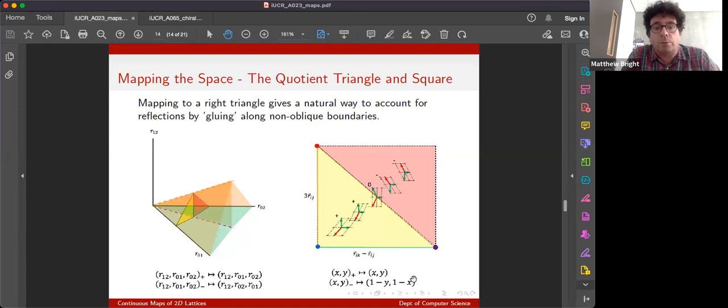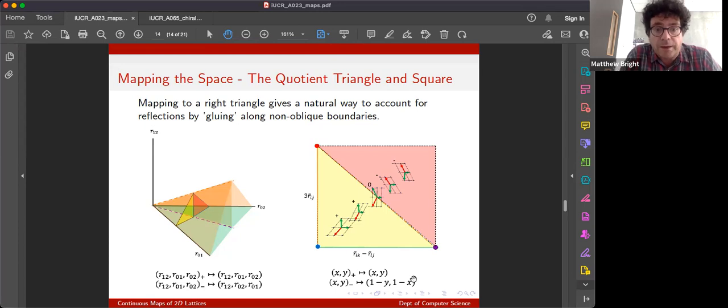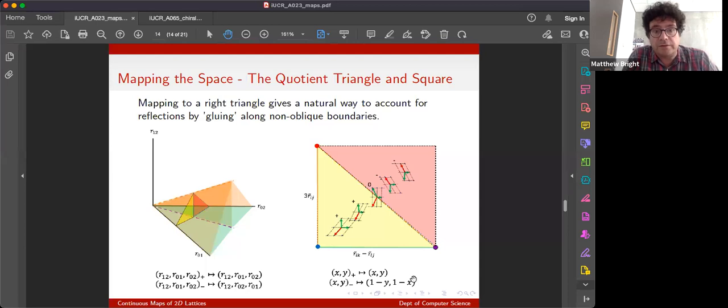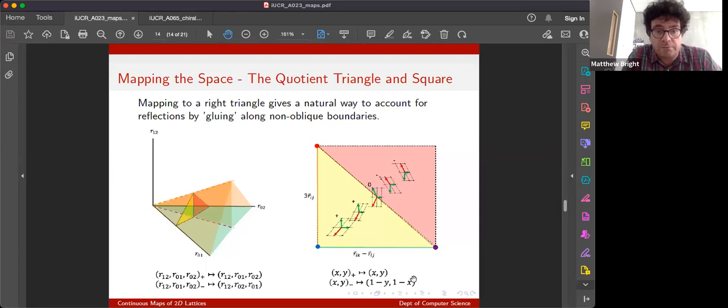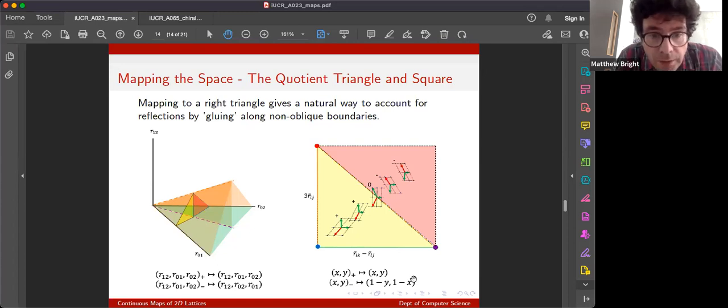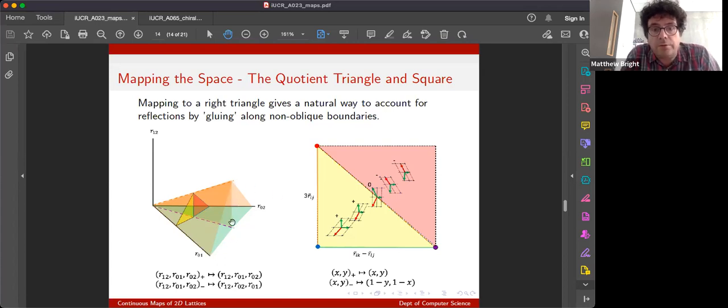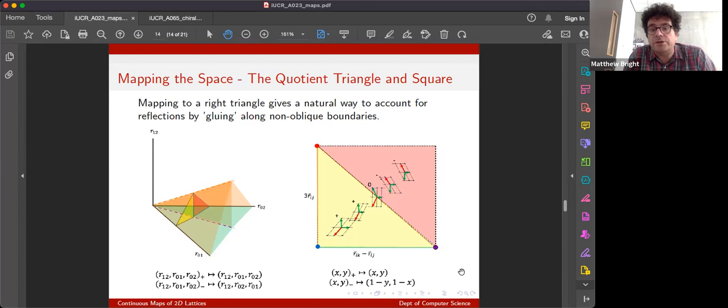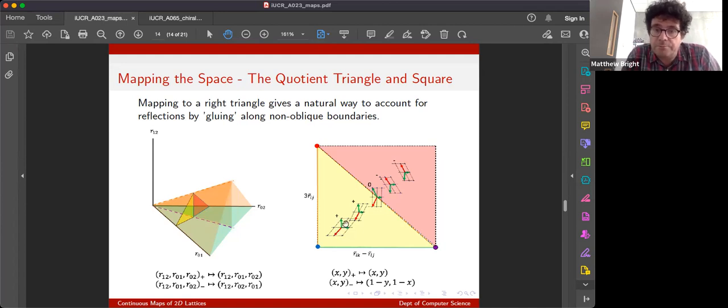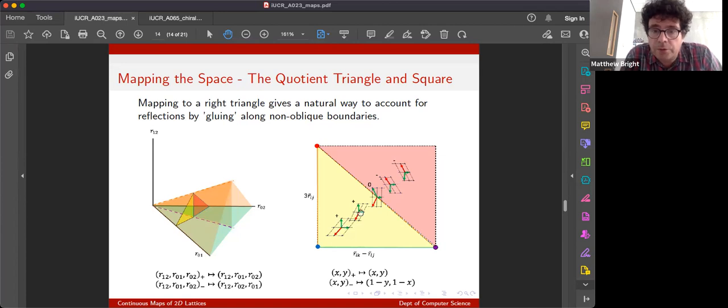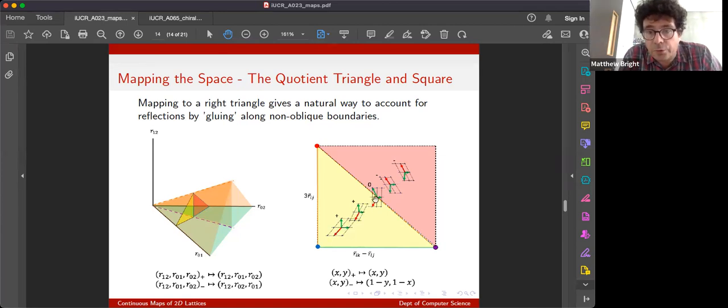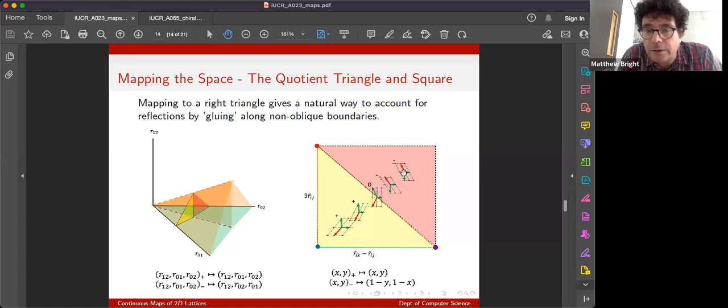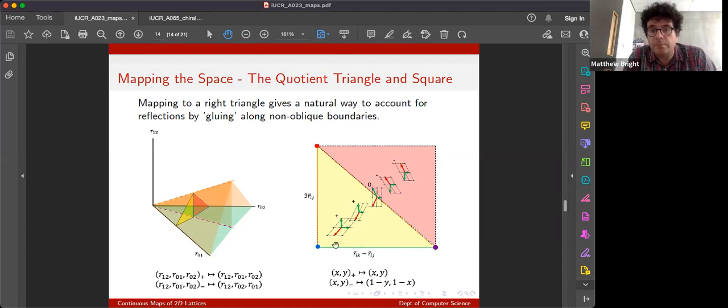How do we visualize that? Well, we kind of pull a little topological trick here. What we do is we take a second copy of the space and we glue it to the original copy of the space along a subspace containing higher symmetry lattices, where the chirality is always going to be equal to zero. So we either, in the three-dimensional case, we have a double cone, we simply map a copy of the cone. And in the two-dimensional case, we have a copy of the triangle across the diagonal. And this hopefully illustrates what you have here. Then you have this continuous space. And if I kind of move in a diagonal path along, across this border, I deform this lattice through a higher symmetry, through a centered rectangular lattice, and back into its mirror image here in the square. So that's kind of schematically illustrates what's going on.